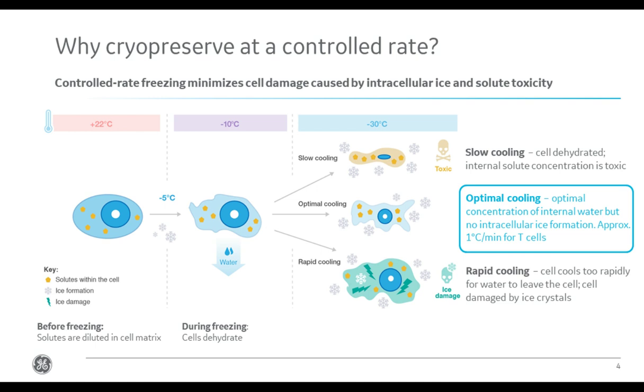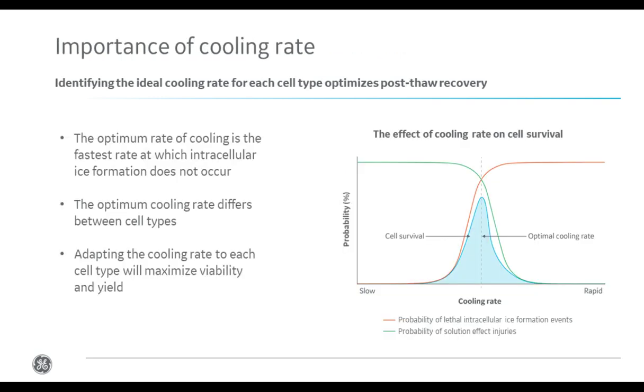Of course, the exact optimal cooling rate will vary depending on each cell's membrane permeability, and so dehydration rate at low temperatures, as well as their robustness to higher cryoprotectant and salt concentrations, which will vary from cell system to cell system. For instance, for T cells, the optimal cooling rate is around 1 degree a minute. It should also be noted that this is the dominant hypothesis for cell death at the moment. However, other factors, including cold shock, membrane oxidization, mechanical ice damage, ATP depletion, and many more factors can contribute to cell damage during the cryopreservation process.